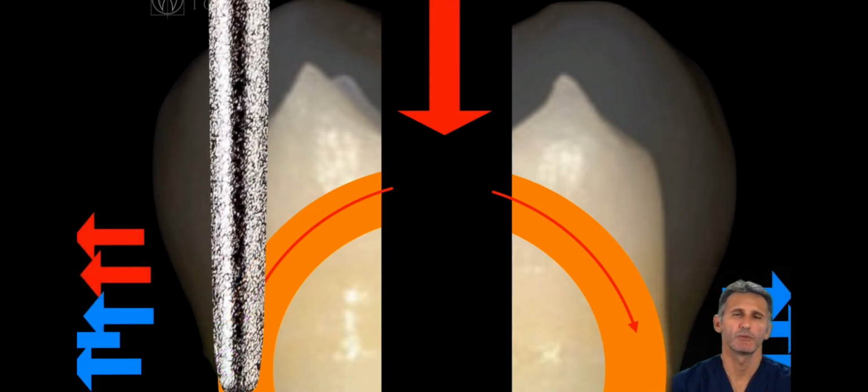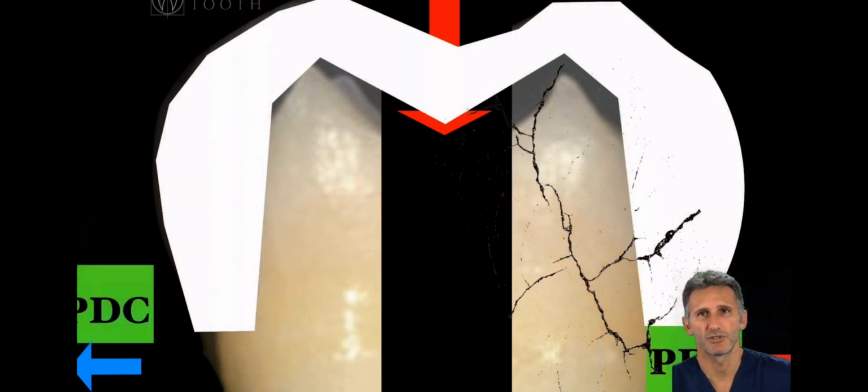When we do a shoulder, what happens? That we remove dentin, so we reduce the section of the most important material, the dentin. And if we do this too much, and if we also put a big endodontic access, like people were doing in the last years, because they were looking for the apex, for the straight access to the canals, for having the complete vision of the pulp chamber, what will happen is that the tooth, despite the crown that is stiffening everything, will develop cracks and will fracture.